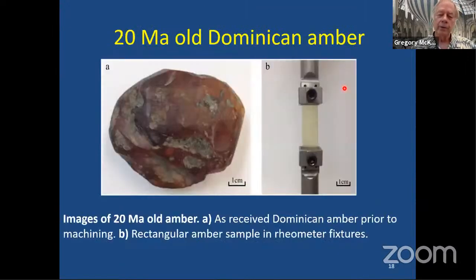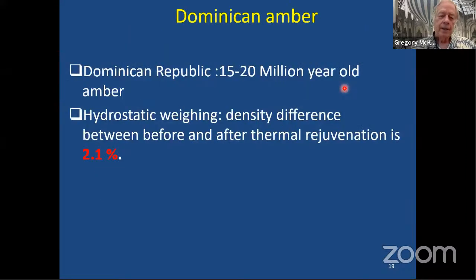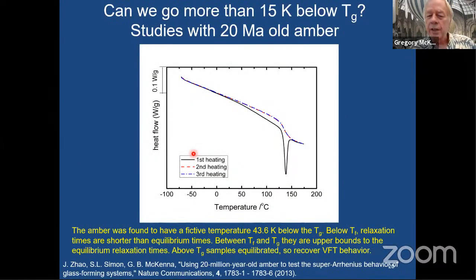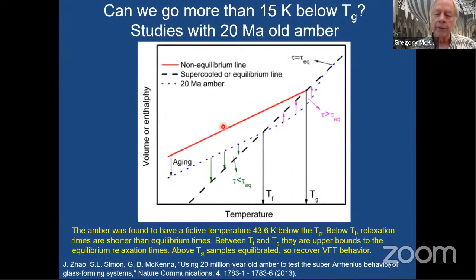So here's my 20 million year old amber again. And keep in mind, these are glasses, and they really do go slowly. And so what we have, from the hydrostatic weighing, is about a 2.1% difference in density between the sample as received and after thermal rejuvenation. And this just shows a DSC experiment. This very large excess enthalpy, what we call overshoot, is typical of a low fictive temperature glass. And we can calculate the fictive temperature. And it turns out that the fictive temperature for the 20 million year old amber was 43.6 degrees below the glass temperature.